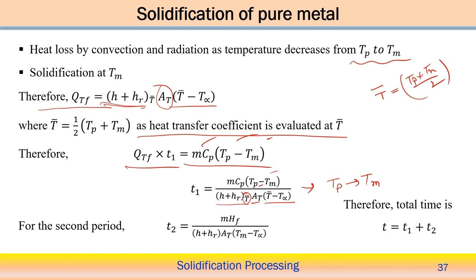Now the second period is the changing of phase from liquid to solid. In that case the total heat content, the latent heat, has to be released, divided by (h plus hr) at the cross section area and (Tm minus T infinity). Here hr is defined at the melting point temperature. The difference between t1 and t2 is that for t1 we define the properties at the average temperature T bar, but for t2 we calculate h and the heat transfer coefficient at the temperature Tm. So the total solidification time is t1 plus t2.